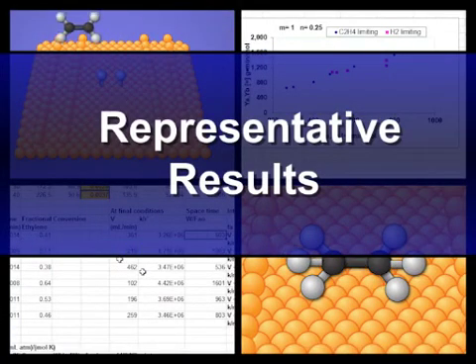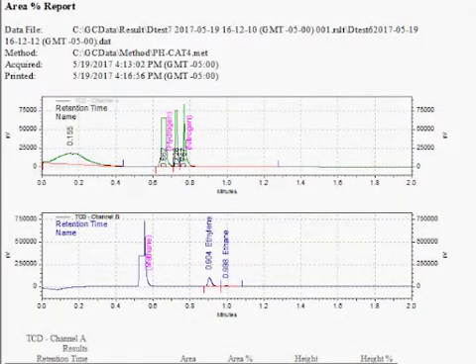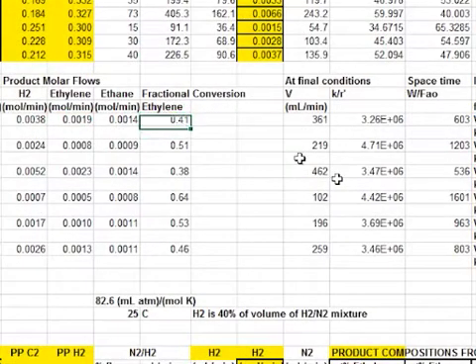The reaction is conducted under both ethylene limiting and hydrogen limiting conditions. Ethane production is measured at different reactant concentrations through gas chromatography. This raw data is converted into fractional conversions and reactant spacetimes.